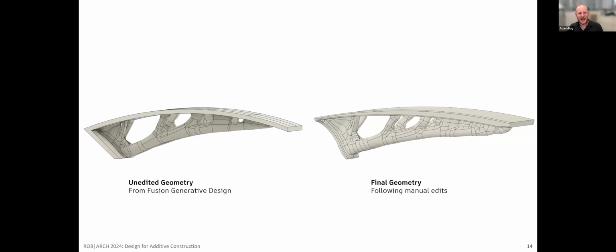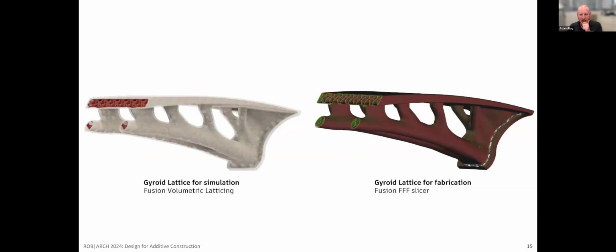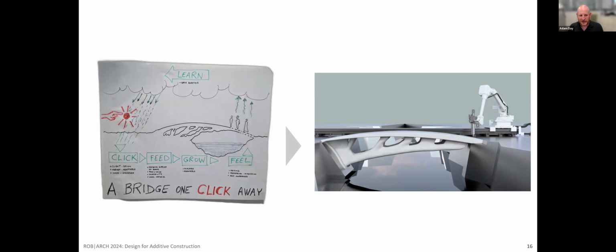And then, of course, a little bit of manual editing for things that we know, or remove particularly difficult members, things like that. And then infill. So for this, we're going to use a gyroid infill for this bridge, which is a pretty typical infill pattern. Initially we did a simulation of using a volumetric lattice infill, but then it turns out that the gyroid infill that we had chosen, your typical FFF style gyroid infill, when we ran simulations on it, worked great and provided plenty of stiffness. So it was an easy choice.